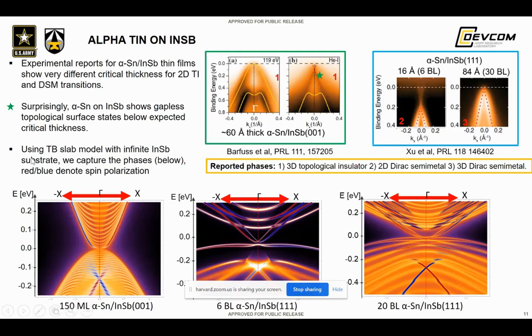But using various models, including a tight-binding slab model, we are able to calculate these on InSb substrates. You can calculate these phases below. The primary difference here is that the InSb substrate, because of its band offset, is very small, on the order of maybe 0.1 eV or less, and it has a small band gap. The techniques to calculate these details are a little bit different from the CdTe material.